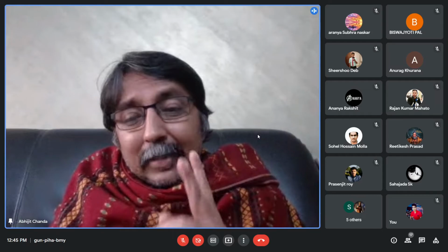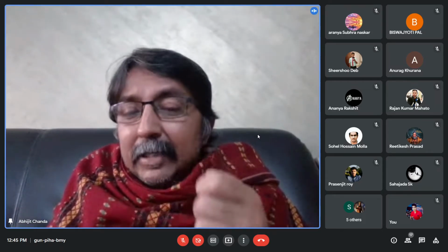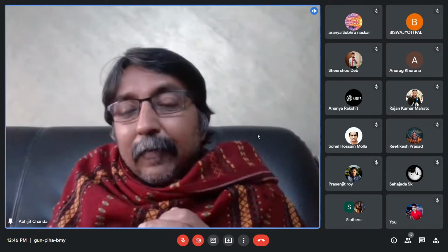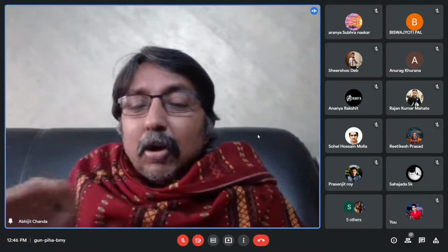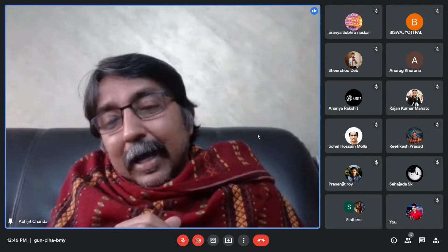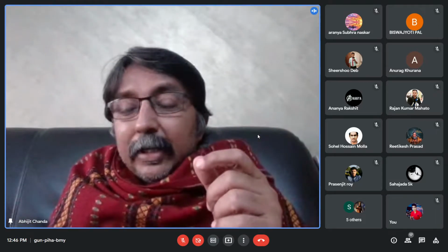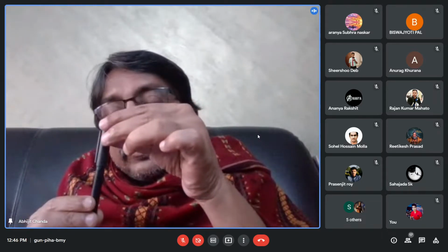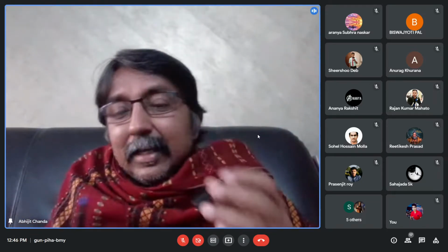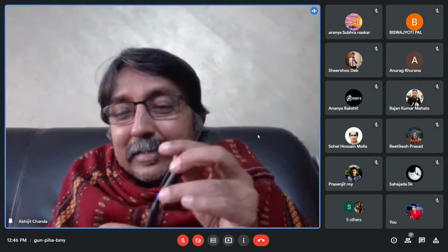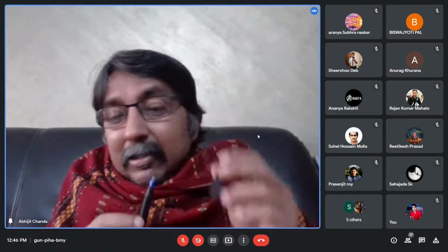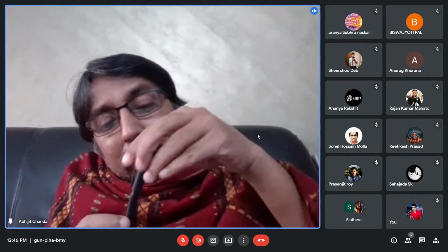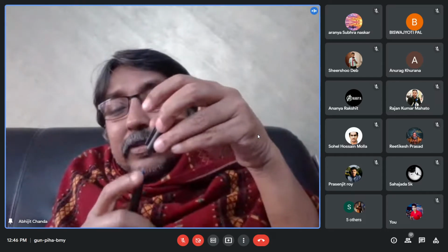What else? Two other things are very important. If you see the broken piece of aluminum, or insufficiently broken, incompletely broken piece of aluminium, you will find the surface is tortuous. The surface is very, very rough. In case of brass, if you take the broken piece, this is the broken piece and this is the original piece, you can bring them together and one will just fit into the other, no problem. You can just put them together and they will just match. Yeah, you will have to use some glue or something so that you can fix it. Otherwise, they can match. But in case of aluminium, once the sample is broken or even not broken completely, partially, if you want to bring it back, the surface is so rough, the two surfaces will not match.